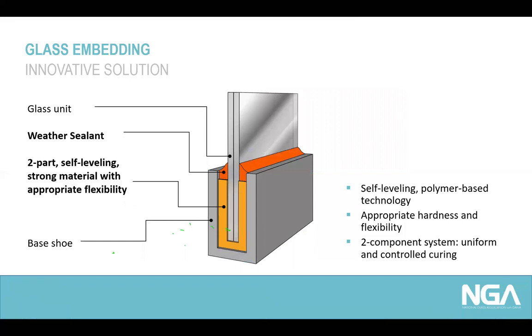So the detail we recommend for projects, for glass railing projects, is quite easy looking like this. So we want to achieve an appropriate, strong support. We want to expose the laminated glass edge to a compatible material, which is our polymer-based grout. And we want to provide a waterproof system to keep water out of the system, because that is also one of the risk factors for incompatibility and for discoloration of the laminated glass interlayer. And at the same time, this polymer-based grout needs to provide a certain efficiency or fast application process and curing